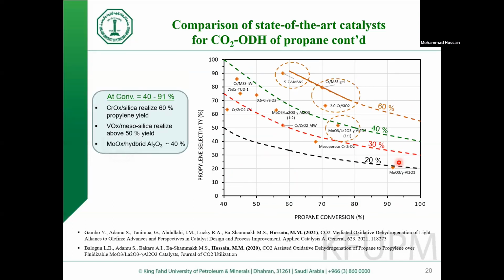There is another class of catalyst where the yield is significantly high. In this case, chromium oxide on silica shows 60% yield. And another catalyst, molybdenum on lanthanum modified alumina, shows almost 40% yield. Now, if someone compares this chromium catalyst and this molybdenum catalyst, of course, chromium is outperforming here. However, one has to consider the toxicity of chromium. So in that aspect, we believe this is a good catalyst to pursue in order to further enhance the yield.